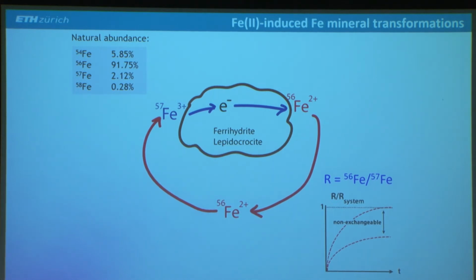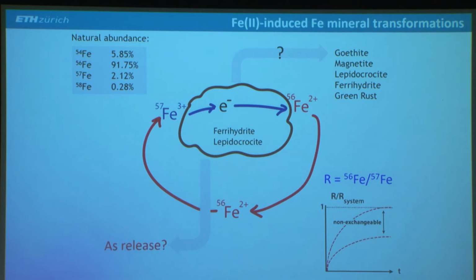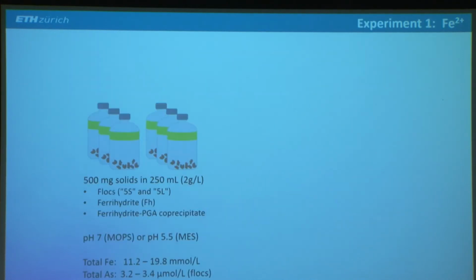And in principle, if everything exchanges, the system will reach an isotopic equilibrium. So if you plot the isotopic ratio in solution over the ratio in the entire system, we should reach a value of 1. But if there's a fraction that is not exchanging at all, that is inert, it will level off at a lower level. Then during this process, we might have mineral transformations, maybe forming more crystalline iron phases, and there could be a release of arsenic if there's recrystallization and a loss of arsenic sorption sites. So let's see what happens.